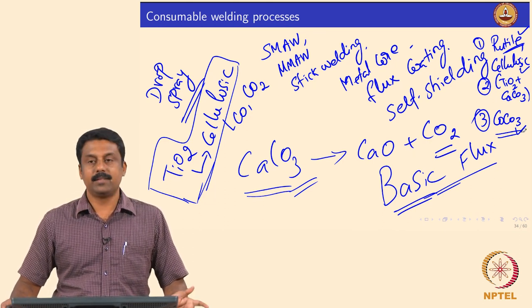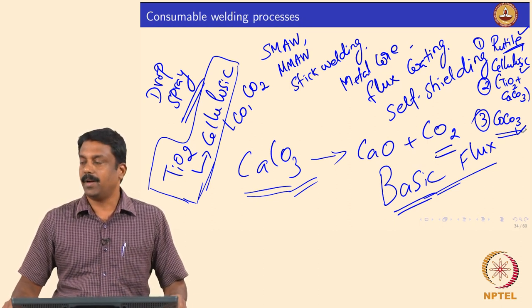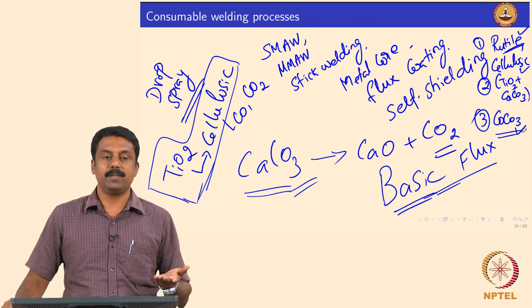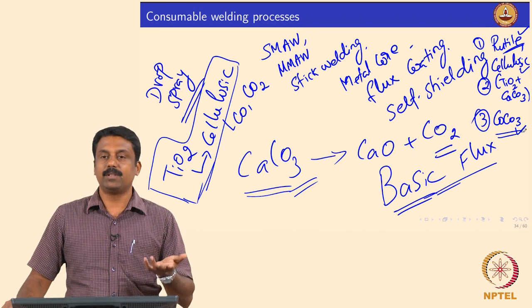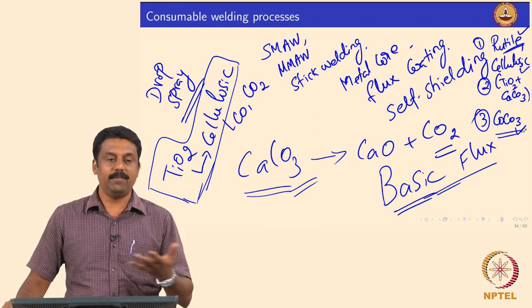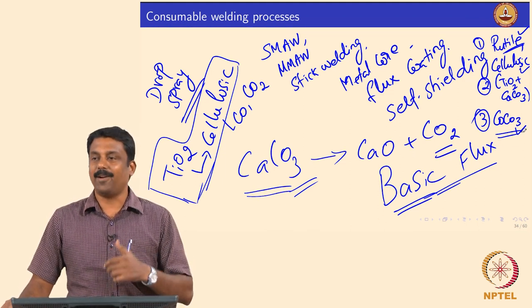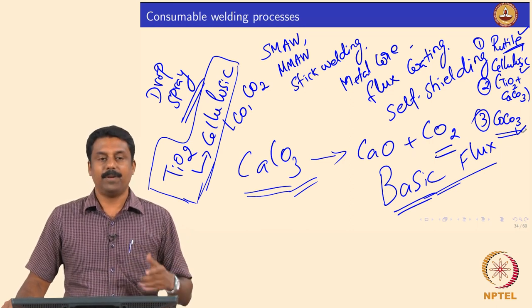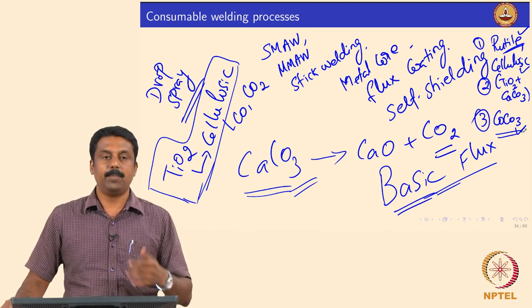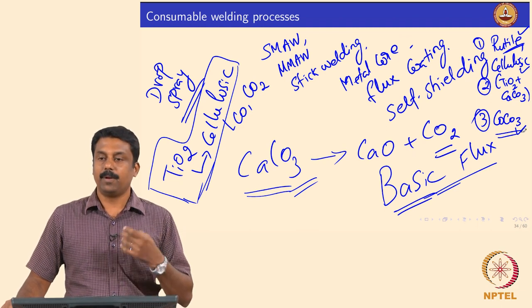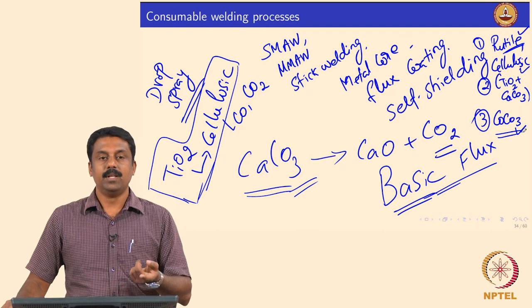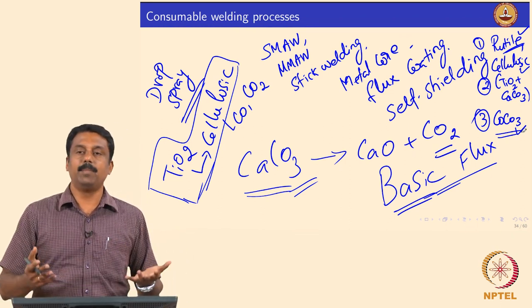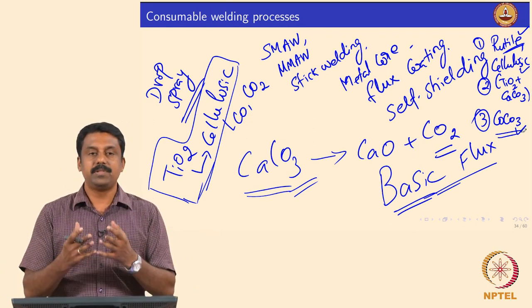Fluxes can also achieve desulfurization and denitrification. Various amounts of these elements can be added to achieve required weld metal properties. Alloying elements can be added via ferro-alloys: ferro-manganese, ferro-chromium, ferro-silicon, ferro-titanium, ferro-niobium. Note that elemental aluminum cannot be effectively added because its recovery in the weld pool is very low due to oxidation. Elements like titanium, niobium, and vanadium are micro-alloying additions that cause precipitates to increase weld metal toughness.